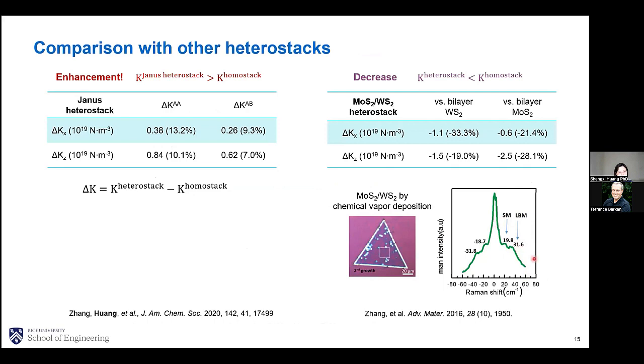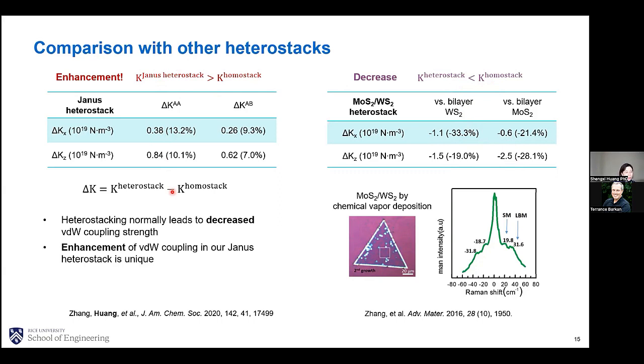Now if we use these numbers to calculate the interlayer coupling strength K, and we compare it with bilayer WS2 and bilayer MoS2, you can see the numbers are always negative. This means the heterostack actually has a lower interlayer coupling strength compared to the homostack. And this is in direct contrast with our Janus heterostack. As a brief summary, so far we have seen heterostacking will normally lead to a decreased van der Waals coupling strength. And our observation of the enhancement of the van der Waals coupling strength in the Janus heterostack is intrinsically unique. Fundamentally, this is due to the vertical dipole in the Janus layer.